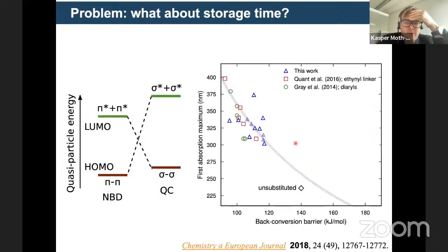So if you look at all our molecules, the correlation between barrier height and the absorption onset more or less follows this trend, that if we have a better absorption onset, we have a smaller barrier. This is the same as saying that the LUMO goes down, the barrier goes down. And we want to be out here with high barrier and good HOMO-LUMO. So how can we do this?